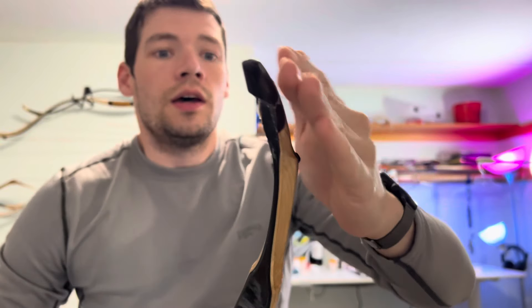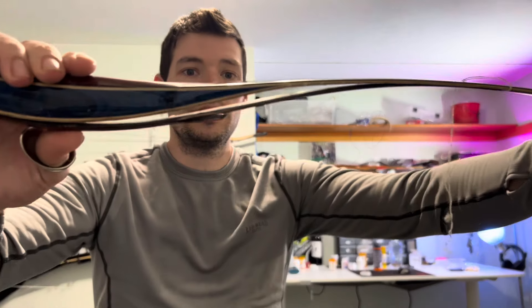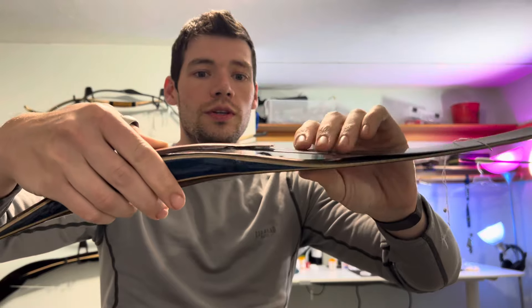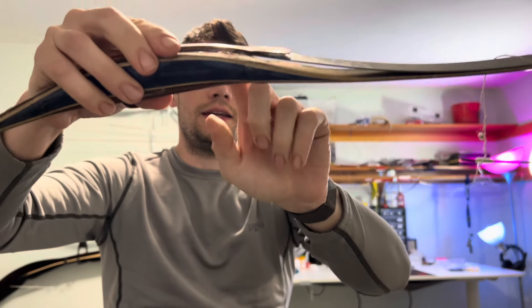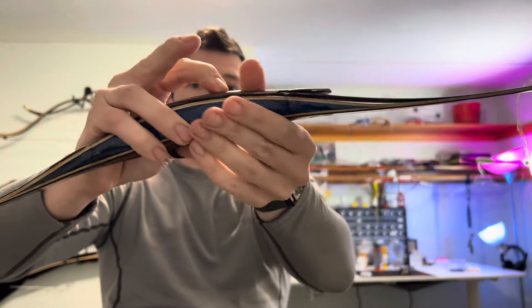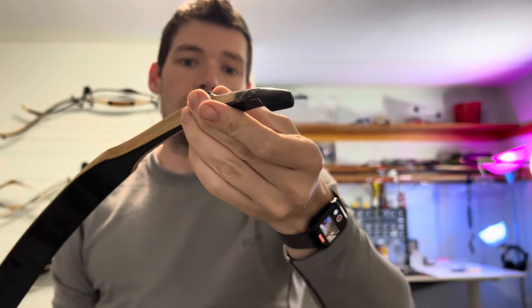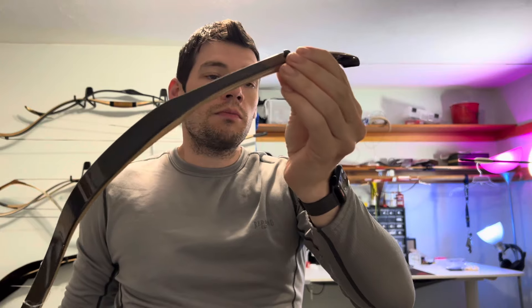If you're watching this, Eucalyptus, I'm so sorry — I'm going to throw you under the bus for this. I've had a few experts look at this bow. There's delamination in the carbon towards the core. This could be fixed since it's not in the core itself — it's just delamination of the layer, you could pull that back on. But the tip is broken — the horn tip is gone, exposing the carbon underlayer.